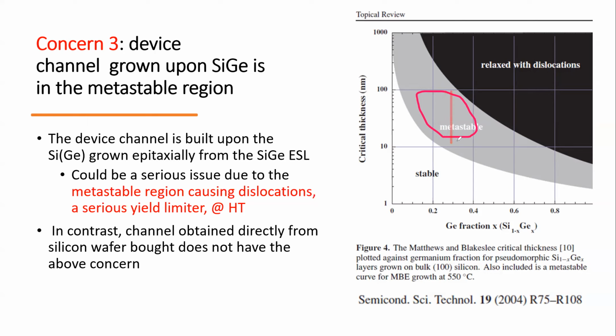You are okay. But why is this region called metastable? Well, because it is not stable. It is not relaxed. It's right in between. And being right in between is not a good thing, because it will relax and form dislocations in this location when you experience a very high temperature anneal, because it wants to relax. All material in the metastable region is not as stable as you think, and it will go into a relax mode. It likes to relax, all right? That's the nature of the layer. If you give it a chance by doing what? By giving a very high temperature anneal, then you're going to have a problem.